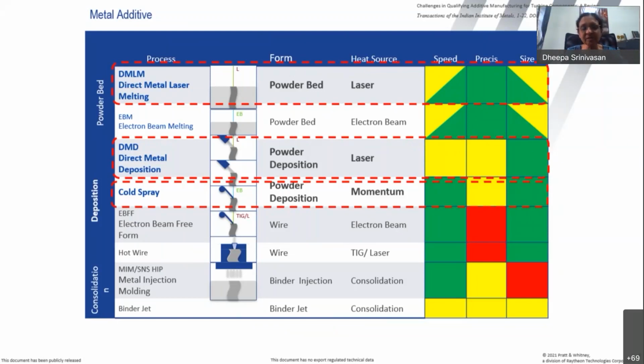It is not so much the material, but with respect to titanium, I would rephrase your question in a different way. Titanium is very, very prone to oxygen sensitivity. So the powders have to be, powders or wires, whatever, but mostly powders, I would say, you have to take a lot of care to handle them, to make them without any oxygen impurity, because titanium alloy is very, very sensitive to oxygen pickup, and the microstructure and everything changes, both in conventional as well as in additive manufacturing. I hope that answers your question.